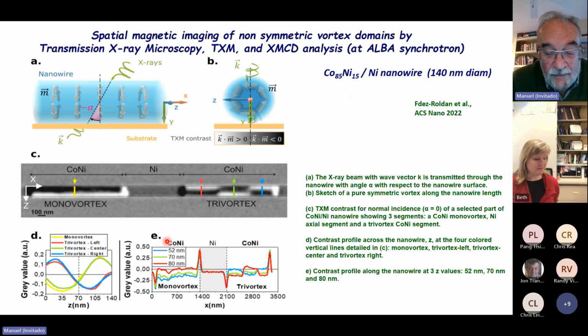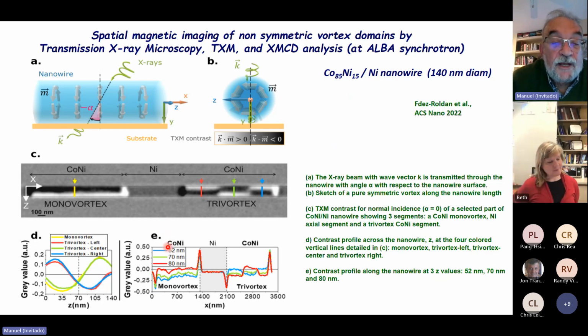So we can determine the distribution of the magnetic moments along the length of the wire, in both cobalt nickel and nickel segments, but also in the radial direction. You see here the experimental results obtained from these measurements, where we see the distribution of magnetic moments depending on the distance to the radius, to the axis of the nanowire. We have here a single vortex in the left part of the large domain.